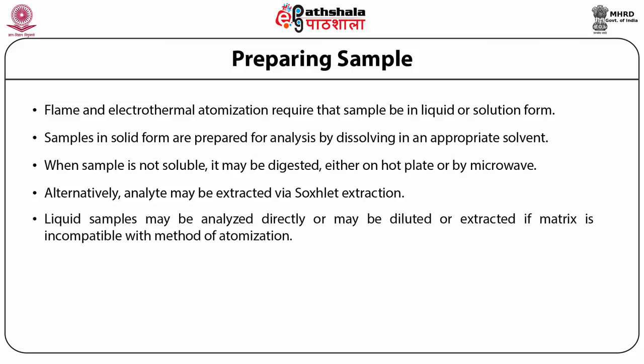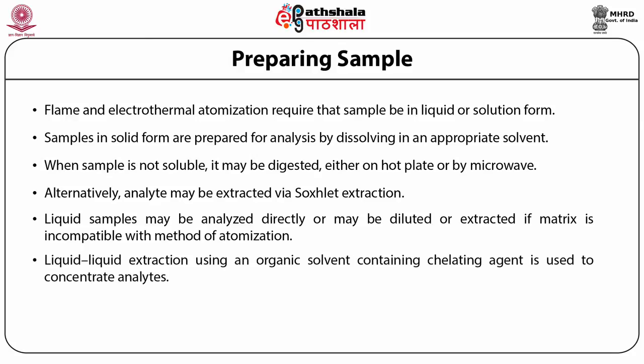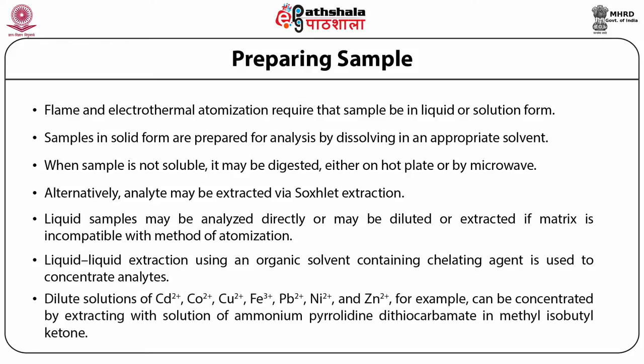Liquid samples may be analyzed directly or may be diluted or extracted if the matrix is incompatible with the method of atomization. Serum samples, for instance, may be difficult to aspirate when using flame atomization and may produce unacceptably high background absorbances when using electrothermal atomization. A liquid-liquid extraction using an organic solvent containing a chelating agent is frequently used to concentrate analytes. Dilute solutions of cadmium, cobalt, copper, iron, lead, nickel, and zinc ions, for example, can be concentrated by extracting with a solution of ammonium pyrrolidine dithiocarbamate in methyl isobutyl ketone.